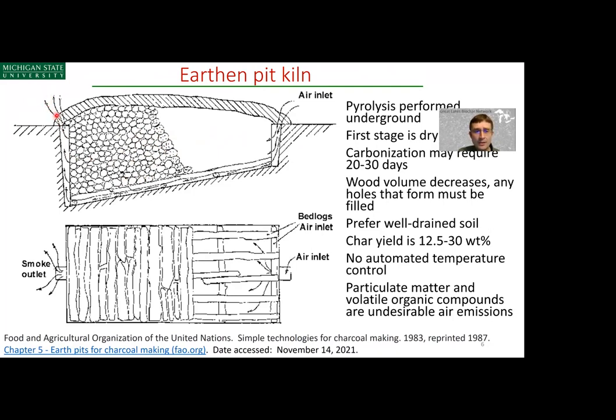These earthen pit kilns are covered with soil, usually sandy or loamy soil. It's important, as this kiln operates and the biochar volume reduces, to fill in any cracks or fissures that form, because those will allow fresh air to infiltrate and cause combustion to occur. So this isn't something that can be done for 20 to 30 days without monitoring. It does take frequent monitoring to make sure that anoxic conditions—conditions in the absence of oxygen—are held.